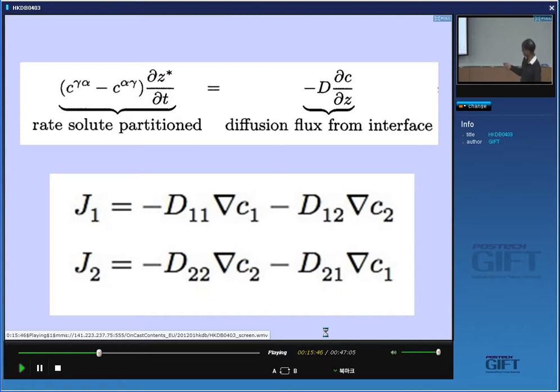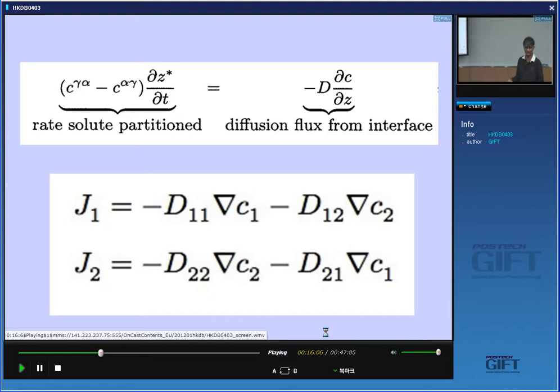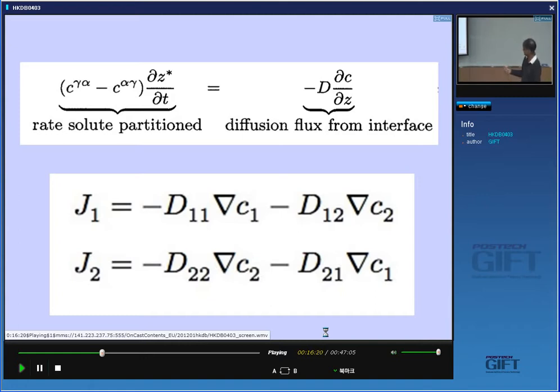It is possible to do this and many diffusion databases will allow you to have a matrix of diffusion coefficients including D11, D21, D12, and D22. But for the purposes of today's lecture I'm going to neglect the cross-diffusion coefficients just to simplify the problem. When using mobility databases they might include cross-diffusion coefficients, but in some cases it's possible to neglect them — for example, the movement of manganese is unlikely to be strongly affected by the gradient of carbon, since manganese moves much, much slower than carbon.